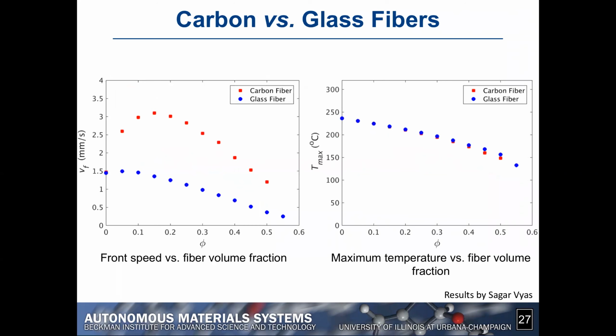So obviously this technology could be used also for glass fibers. Right? Glass fibers are much less conductive than carbon fibers, so their effect on the speed of the front is substantially less than what we observe for carbon fibers. Carbon fibers are in red, glass fiber results are in blue. With regards to the maximum temperature, it doesn't make that much of a difference.